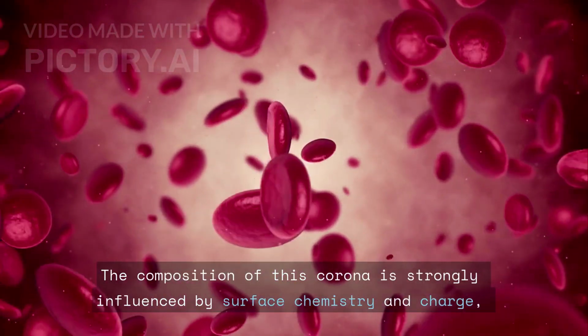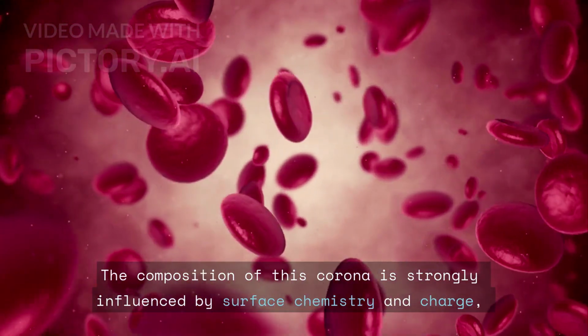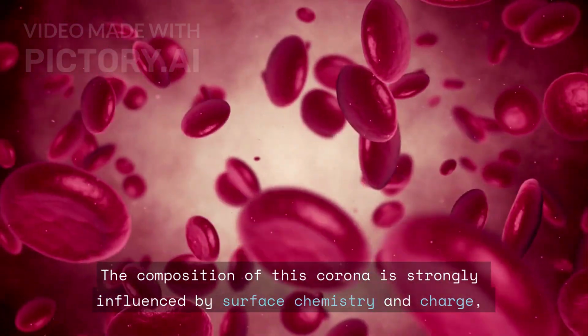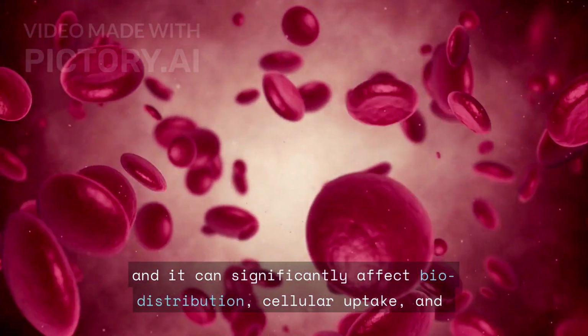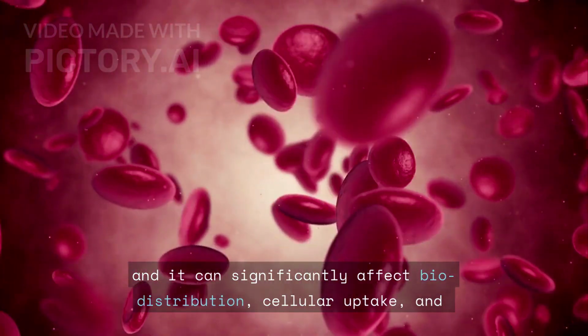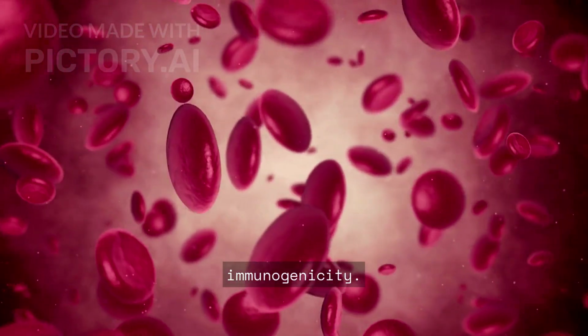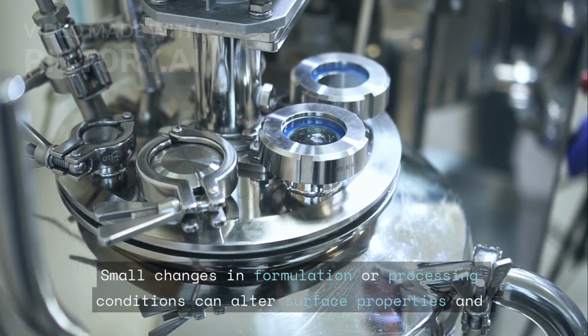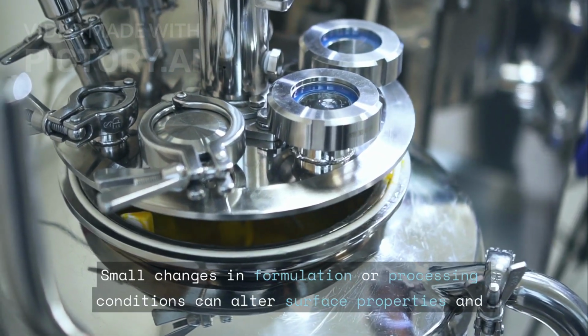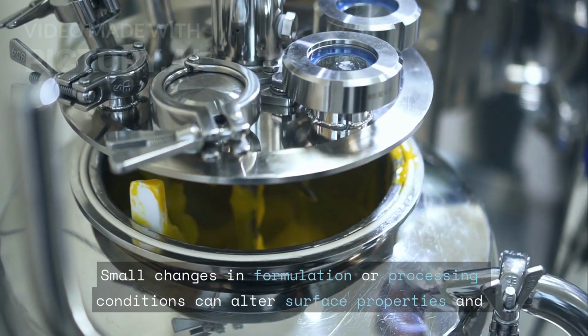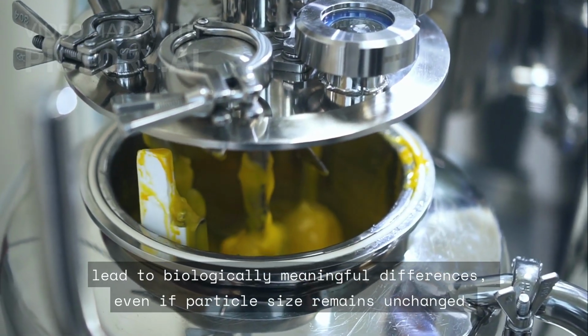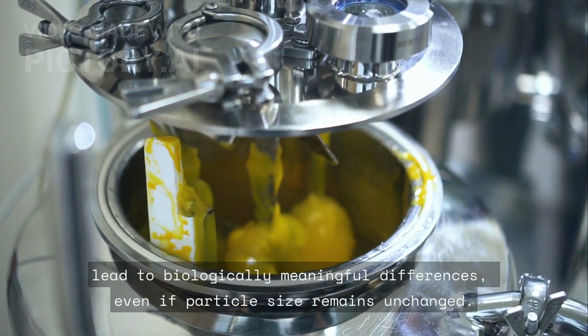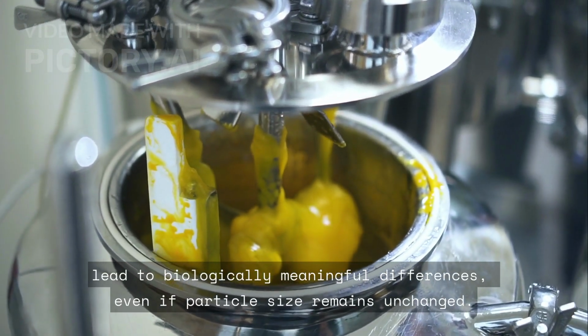The composition of this corona is strongly influenced by surface chemistry and charge, and it can significantly affect biodistribution, cellular uptake, and immunogenicity. Small changes in formulation or processing conditions can alter surface properties and lead to biologically meaningful differences, even if particle size remains unchanged.